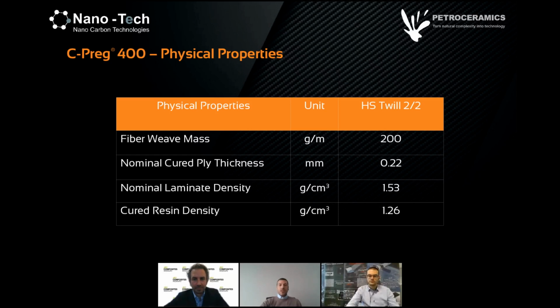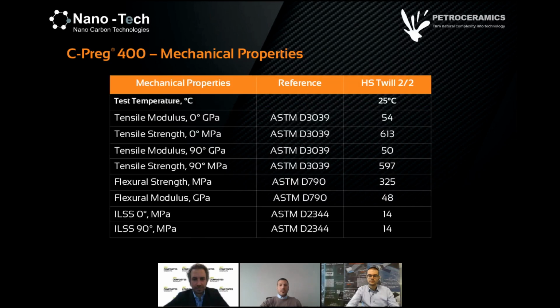This is the one that we have best characterized. So let's see at a glance some mechanical properties of the material. Here you can see a characterization at room temperature of the material with ASTM standards. As you can see, the modulus and tensile strength are comparable with the epoxy system at room temperature. What is not comparable is the interlaminar shear strength, but as I say every time, you cannot bring an epoxy system at 400 degrees.